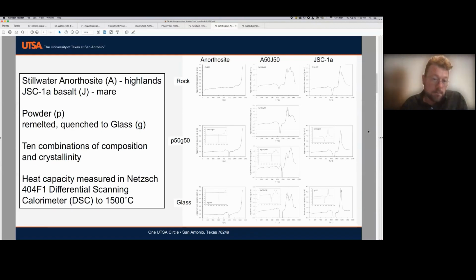So we used an anorthosite from Stillwater, Montana as our highlands analog. We used JSC1A, which is actually a basalt from Arizona, as our lunar mare analog. And we also mixed them together, did a 50-50 mixture. We also took both the original powdered material. For the anorthosite, we actually got a rock and then we powdered it in the lab, and that's all crystalline. JSC1 actually is about 50% glass to begin with. But in both cases, we completely remelted it in a high temperature muffle furnace, poured it out on a plate, quenched the glass, smashed it, powdered it. So we had our initial powder, and then we also had a glass powder. So we did 10 different combinations, different compositions, and different crystallinities.